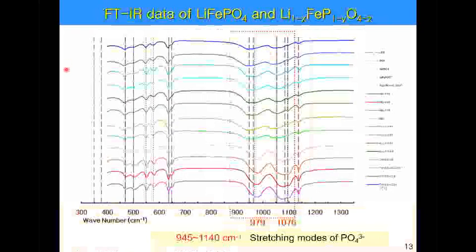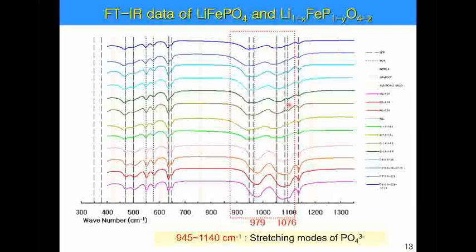Reduced LFP can also be characterized by FTIR analysis. The oxygen-poor environment affects the stretching vibration of the PO4 group. As presented here, we can see a shift in the PO4 stretching frequency compared to normal LFP.